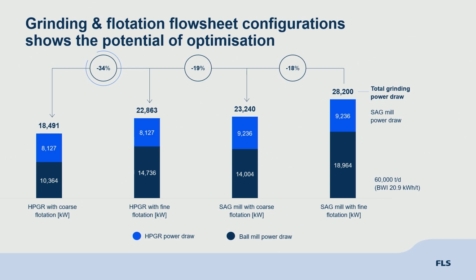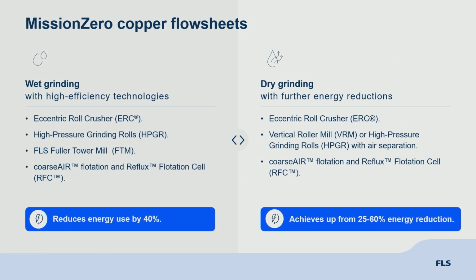But then if you went back to the fine grinding and took the SAG mill out and put an HPGR in, you could reduce it by 19%. And then if you did coarse flotation with an HPGR ball circuit, you could reduce it by a further 34%. So following on from this, we decided that, okay, this is great as a desktop study, but we really do need to do some test work on this and test each stage of the process, put it into a full engineering study, and look at the results.